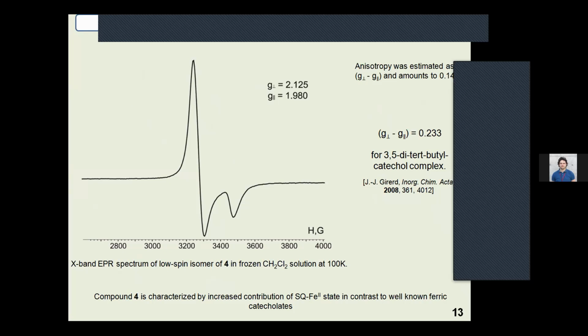The low spin signal is shown to be pseudo-axial. Anisotropy was estimated as the difference between these two values and amounts to 0.145. It should be noted that in comparison with the previously published data for 3,5-di-tert-butyl substituted catechol, in our case we found an increasing contribution of the semiquinonate ferrous state, in contrast to the well-known catecholates.